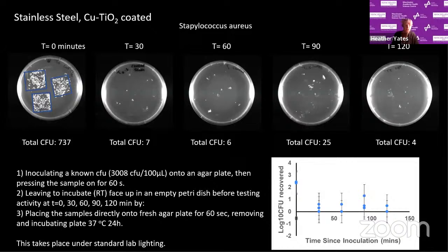and the bacteria allowed to incubate. So the first one at 0 minutes with the little blue squares around, you can see the amount of colonies. And then over time, 30 minutes, 60 minutes, 90, and so on, you can see a total drop in the number of colonies. The information is also put in the graph on the bottom right, showing the log reduction. So this is a log reduction of about 2,